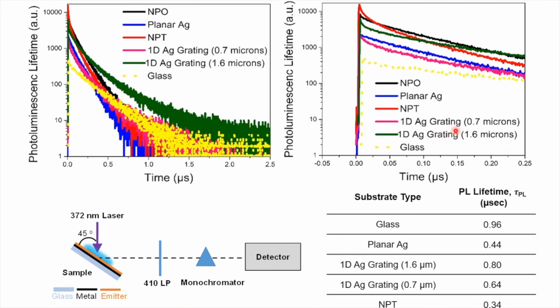The gratings, though, even though they do enhance the stability, they actually increase the lifetime compared to the planar silver. So that really does not suggest that the same mechanism is causing stability enhancement for the gratings compared to the nanoparticle silver. So essentially, we have to dig into that data a bit more. There are probably changes in the non-radiative rate that are also affecting the stability. And this should be figured out by taking the quantum efficiency measurements. We also saw a size dependence of the stability for the nanoparticle metasurfaces.